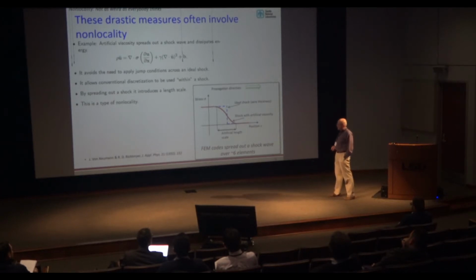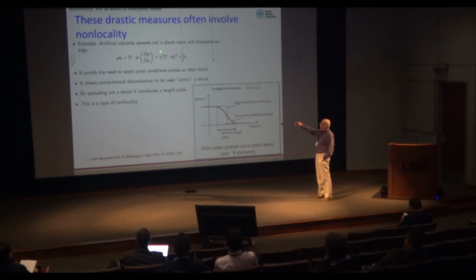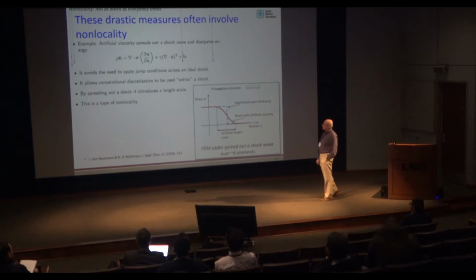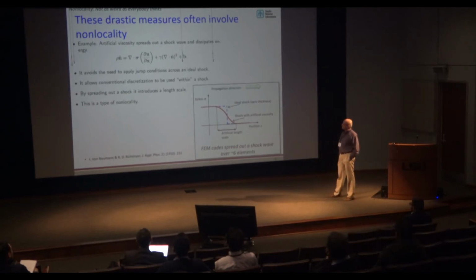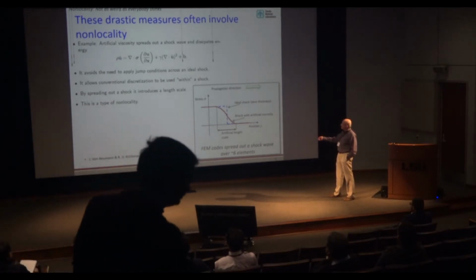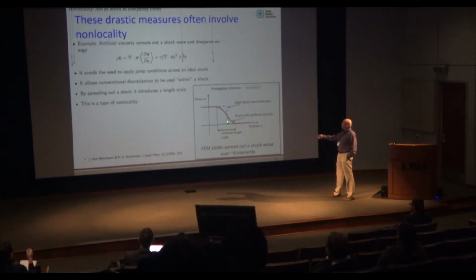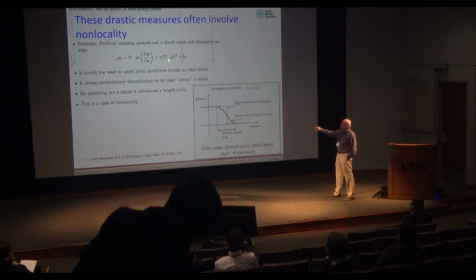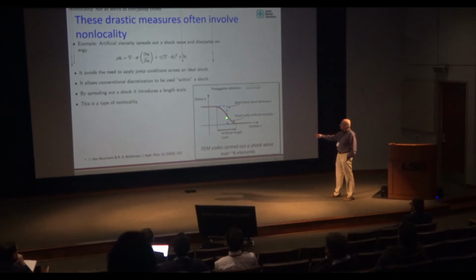So the way everybody mitigates that problem is to use artificial viscosity, which was introduced by von Neumann almost 70 years ago. And that consists in modifying the PDE to include this term that involves the derivatives of the velocity. And the effect of that is where there is a jump in velocity, this term gets big, so it introduces a stress, in effect, that spreads out the shock wave into this type of curve. And after that, everything's fine.